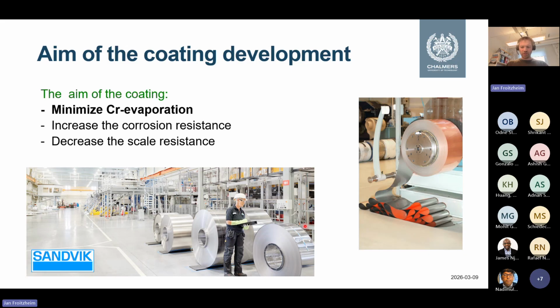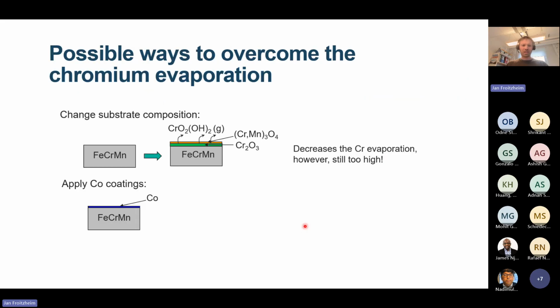So, we want to minimize chromium evaporation. How do we do that? With typical steel, iron chromium with maybe 0.5% manganese, you get an oxide scale consisting of the chromia scale I mentioned before, and on top of that, a chromium manganese spinel.